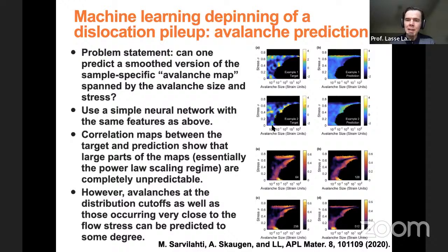But what we can do is correlate these two, the target and the prediction. These are shown here, and these are actually for different system sizes. What we get here is that there's a large part of this map that is completely black, which means that the correlation between the target and prediction is zero. So there's no predictability. That actually means that we are in the power law part of the avalanche distribution, where you have these truly critical avalanches that we cannot really predict. This is to be expected.